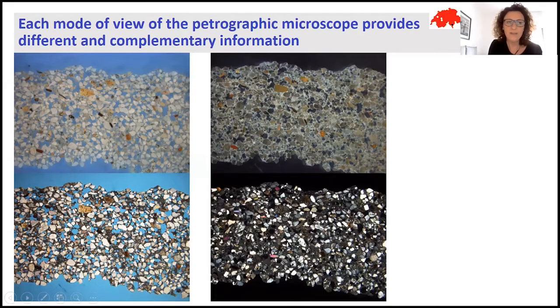The third image is the one with transmitted light. In this case, we can observe the different aggregate and binder percentages, and the voids. For example, in this case, you see this blue, which is from a special preparation with blue resin, which is better to identify the porosity, because what you see in blue are the voids, so the porosity of the mortar. The last mode of observation is the one with polarized light, and in this way we can also characterize the different minerals that are present as sand or as binder in the mortar.